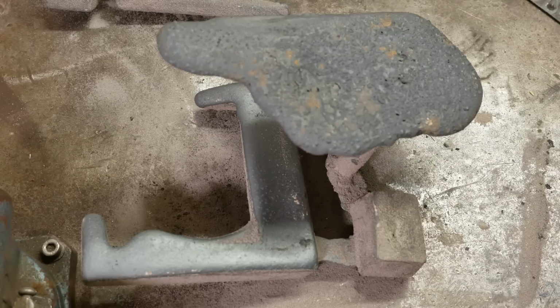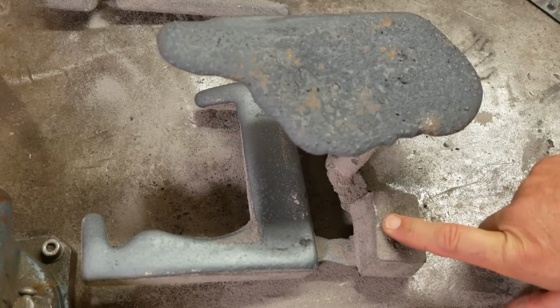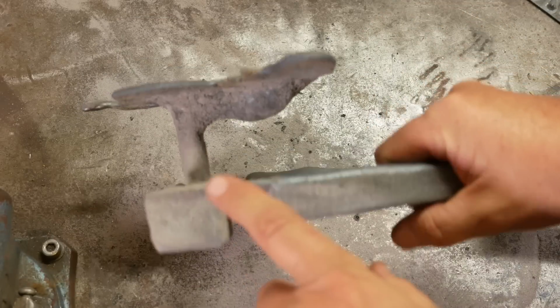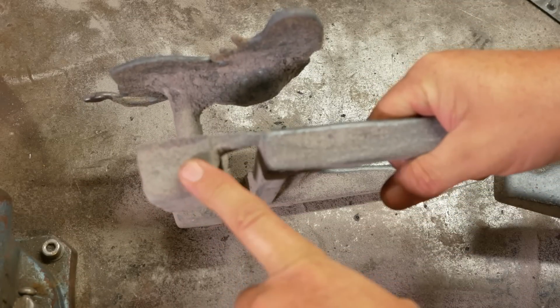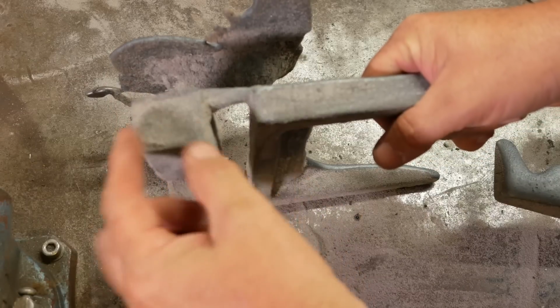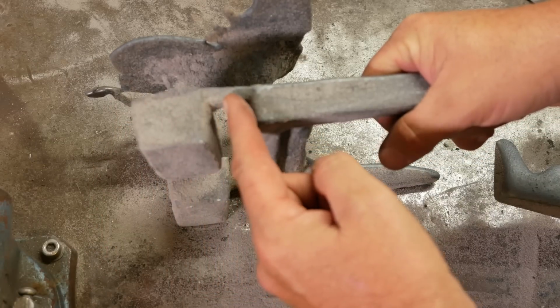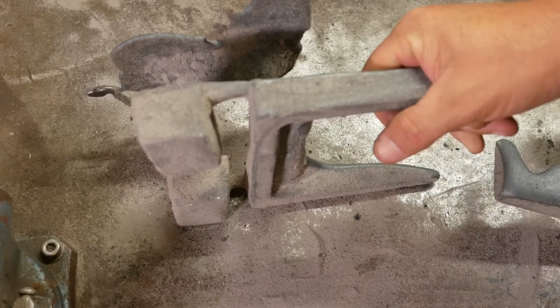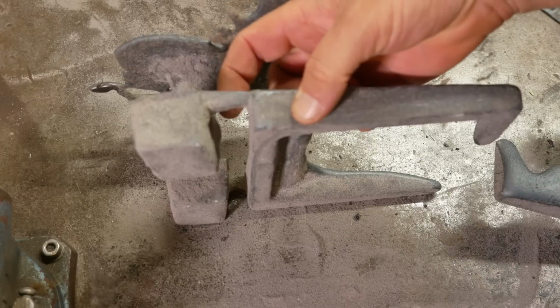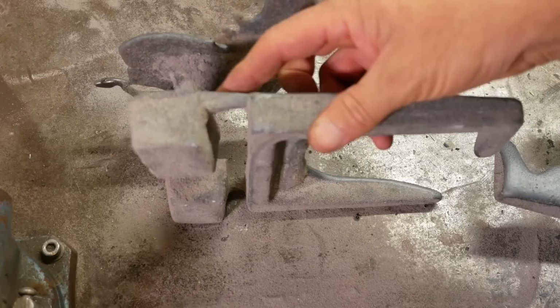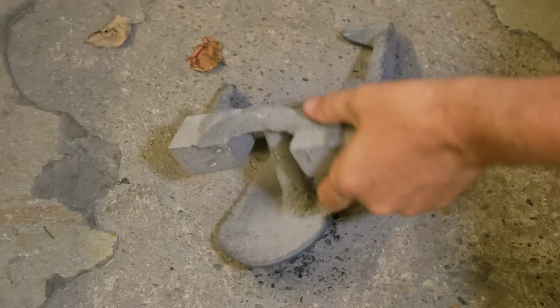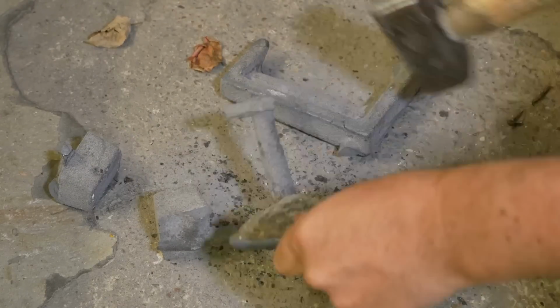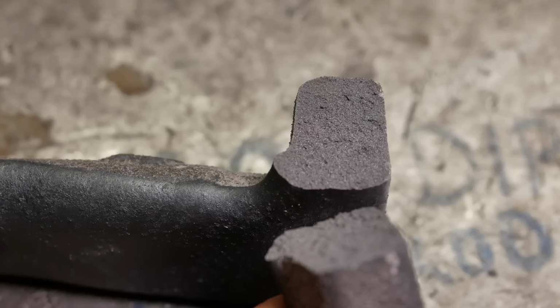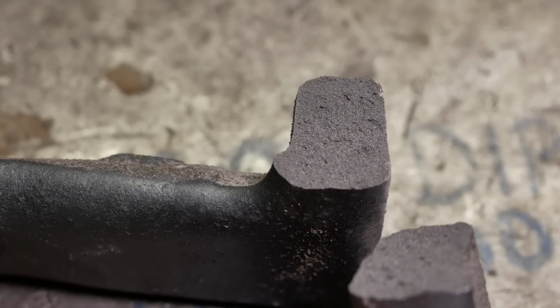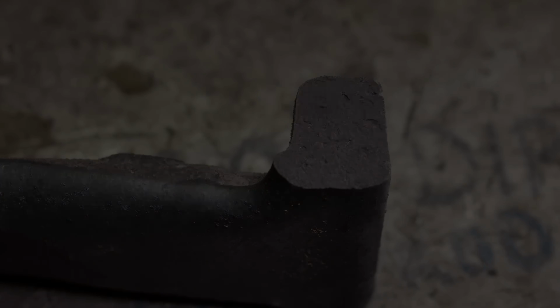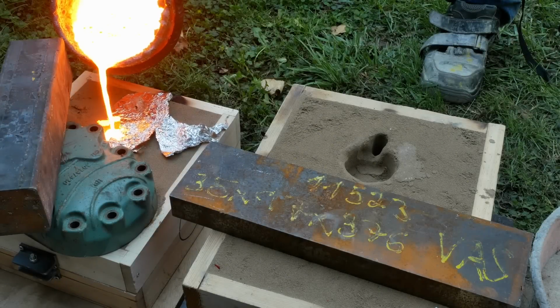So the two major things I need to do when I redo this casting: I think I'll keep the shrink bobs in the drag, in the bottom part. I'll put the shrink bob much closer to the actual pattern, so there's only a small gap there. And then I'll make that gate much larger so that it can feed really easily. You can see from the fracture surface that I've got nice grey cast iron, so no worries with chills on a section that thick. Doing iron castings is a huge amount of work, so it was a few days later